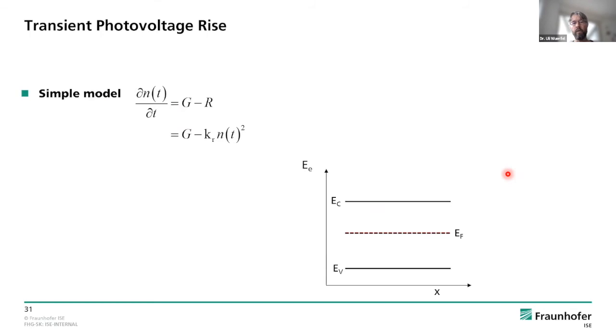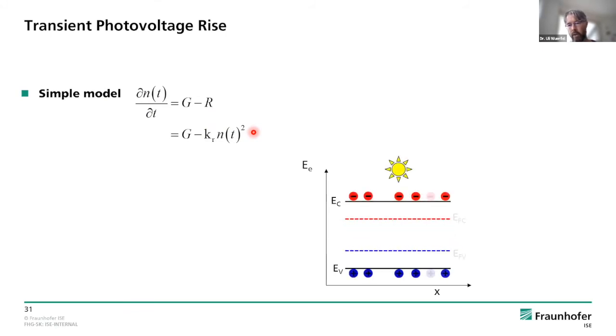Yeah? If you go for a very simple model, you can say the temporal evolution of the charge pair density n is given by generation minus recombination. And for the recombination, we can assume in this case just a square behavior. So for example, radiative recombination goes with the charge carrier density squared. Yeah, it's just an example. It's a very simple model. It would then look like this. You shine light, you create charge carriers, you separate your quasi-Fermi levels, and you measure your VOC. Very simple.